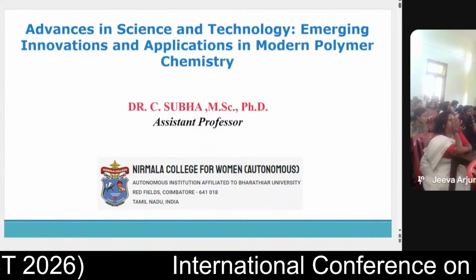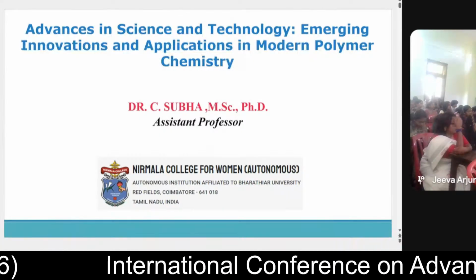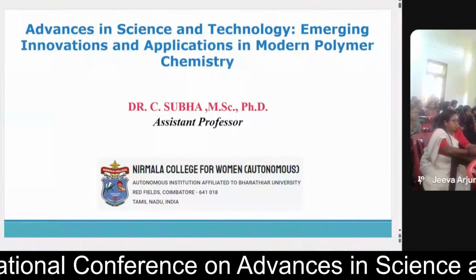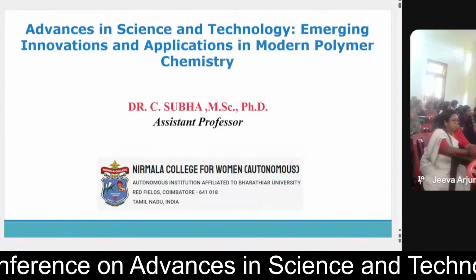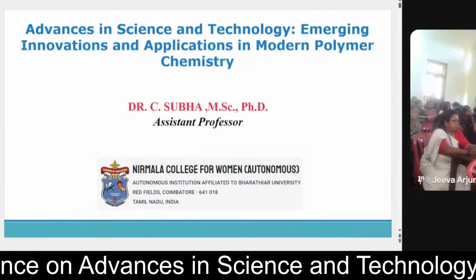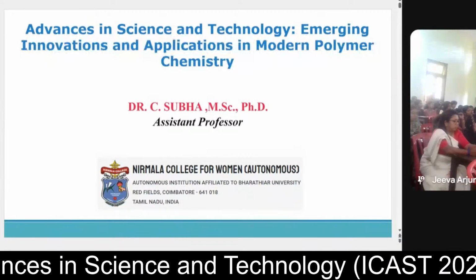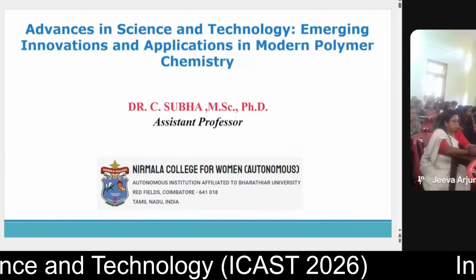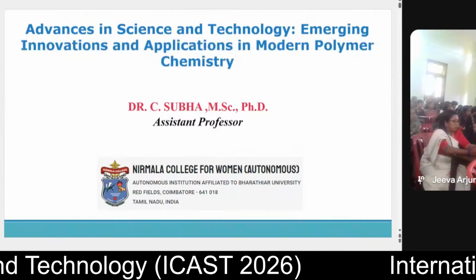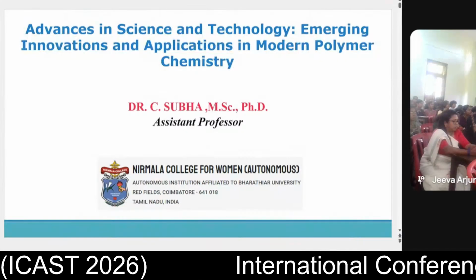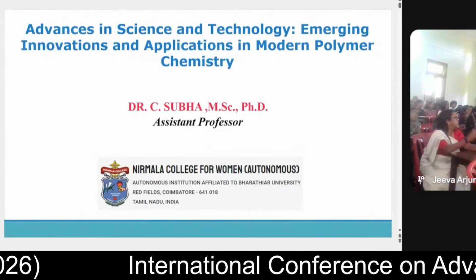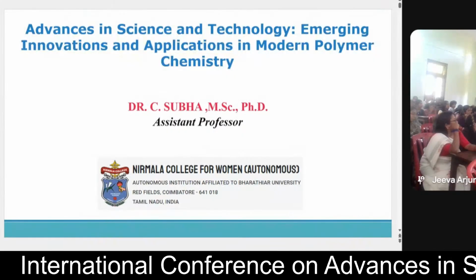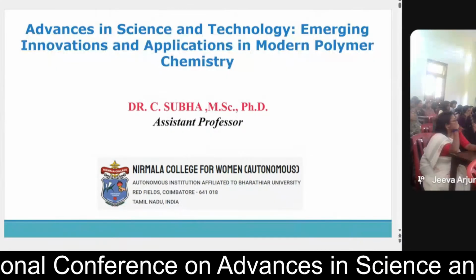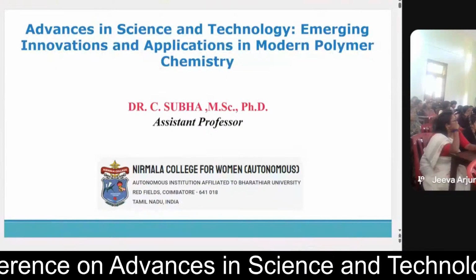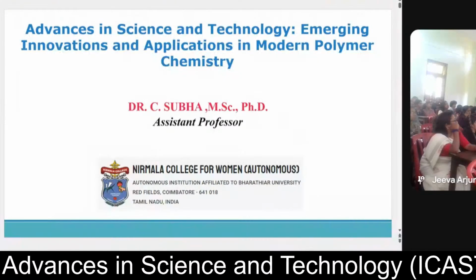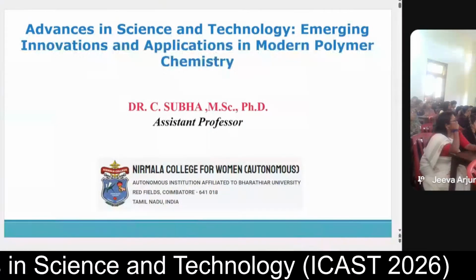stability. See, this is the data we have observed for the polyesters and for the polyamides. Look at this 10% weight loss. Polyester P1 starts degrading at 110 degrees centigrade. This is for the polyamides. It starts degrading at 130 degrees centigrade. The first 10% weight loss is water or moisture, if present, or occluded solvents, which can be eliminated at the first 10% weight loss. So when you compare the polyester value and polyamide value, polyamides are more thermally stable than esters.